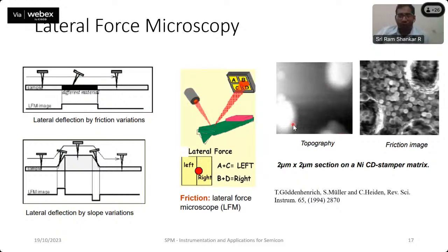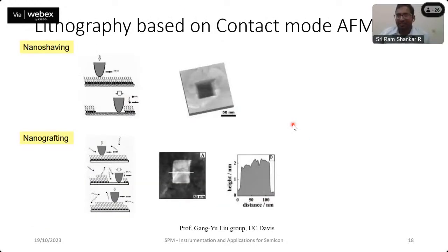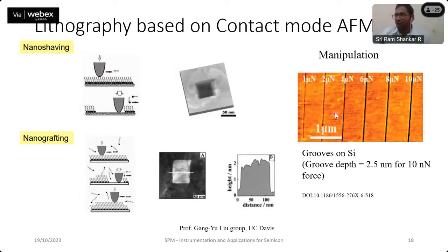If you are not careful enough with respect to the forces that you are applying on the sample, you can end up removing material from the sample. So such marking can be done using an AFM tip. So these are lines that have been marked on a silicon wafer by using different forces applied between the tip and the sample. Okay, so at about 10 nanonewton force, the groove that you are able to make on the silicon is already 2.5 nanometer. So we need to be really careful about the forces that we are applying so that we don't end up damaging the sample.